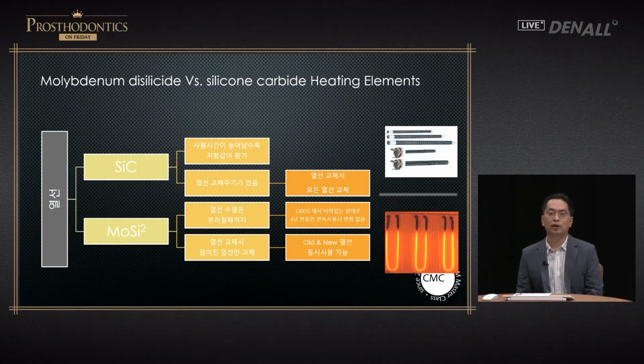There's another change in the past. In order to sinter zirconia, molybdenum disilicide heating elements were used in sintering furnaces. The reason is, as for the 3 mole partially stabilized yttria zirconia, it required over 1,500 degrees of temperature. In order to achieve this, molybdenum disilicide heating elements were required to maintain such high heat. But for 4 mole or 5 mole yttria partially stabilized zirconia, in most cases, the sintering temperature is 1,400 to 1,500 degrees. Therefore, silicon carbide heating elements can be used. These days, we use silicon carbide heating elements, and in the past, we used molybdenum disilicide heating elements.